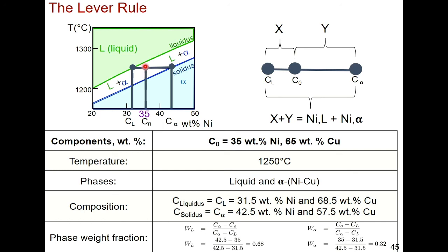Question? Yeah, that 68.3%, that's the temperature factor? Yes, that's exactly at 1250 C. Let's say you're at 1249 C. That will be different, right? So it has to be at a certain point, right? I'm talking specifically about C naught equals 35 weight percent nickel, and temperature is 1250 C. These two numbers, W_L and W_alpha, the phase weight fractions for liquid and solid alpha, are exactly for that composition. Yeah, so it's all based on the tie line and the lever rule.